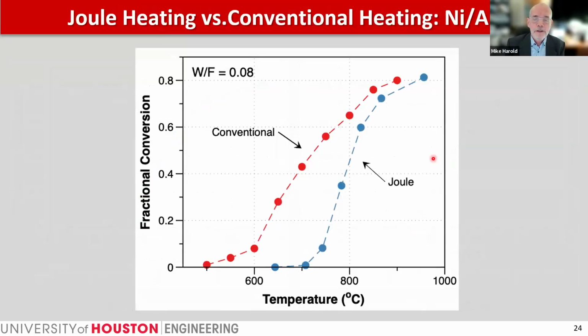Now, additionally, with alumina, we never see a range of temperature wherein the Joule heated wire outperforms the conventionally heated wire. The conventional heating always gives a higher conversion of methane at a given temperature than the Joule heated wire when alumina is the support. Again, that is not the case with zirconia, as I showed you earlier.